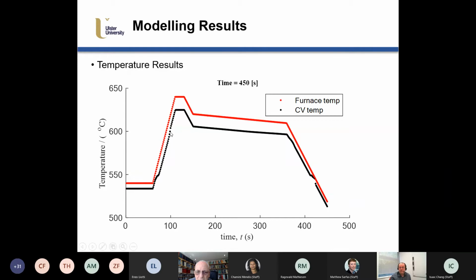So the first advantage here is we've modeled the heating phase and the solidification, and the furnace is in red, and the central CV control volume is in black, and you can see the effects here of latent heat. So you see eutectic latent heat recalescence, or not, well, this change here is due to eutectic transformation. There's very little recalescence, but it's very, very sensitive to this issue of recalescence. So that's why we had to pay particular attention to it. It's right on the cusp of recalescence, I would say.